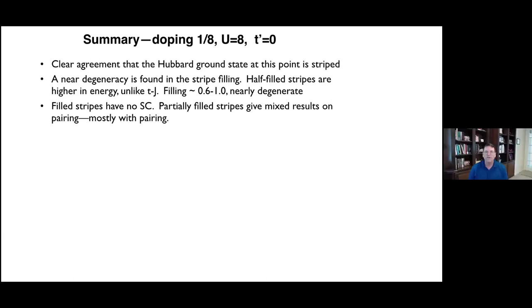The Coulomb interaction, we did analyze that at a mean field level, the long-range part of the Coulomb interaction. If you just put too many holes in the same place, like a filled stripe, it doesn't like that. So it shifts everything more towards half filling. That is one effect. It pushes it in the right direction to compare with experiments. And the other effect that also seems to do that is a t prime. There's some work that I'll point out by Philippe Corboz that shows that.